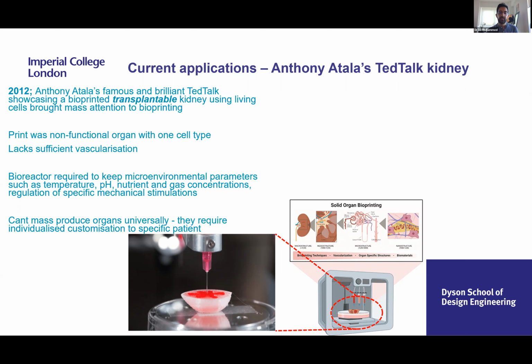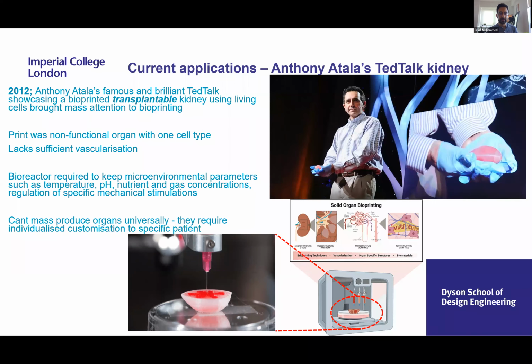This means that it can't be mass-produced universally, as it requires individualized customization, as the process is very slow and long. And a point about vascularization is that because it was printed using a nozzle extrusion, the vascular structure was very, very limited and did not reflect the actual vascularization you get in real tissue.